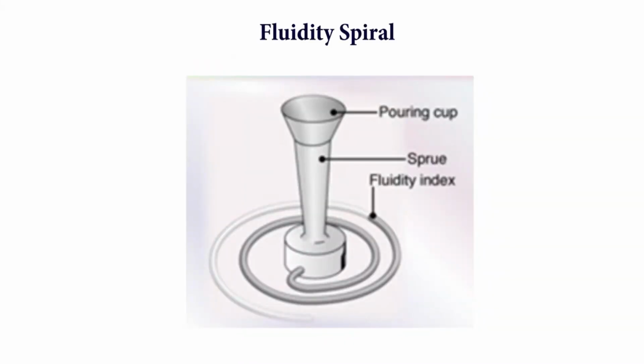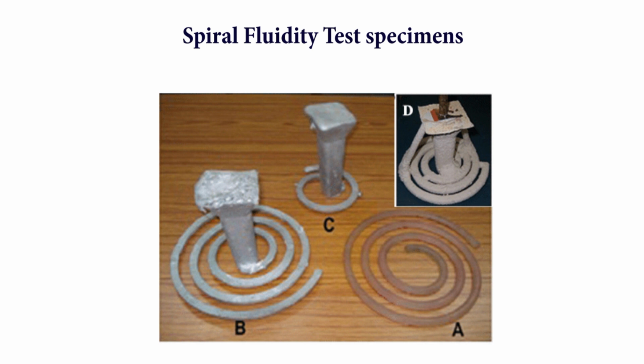Fluidity is an important characteristic of molten metals and alloys, and it directly affects the casting soundness and metallurgical quality. Fluidity is the capacity of molten metal to flow within a flow channel or inside the mold over a defined distance. The most common fluidity test used in foundries is the spiral fluidity test. A few samples of the spiral fluidity test are shown in this figure. In this method, the liquid metal is poured in a mold forming a long thin spiral, and the length into which the metal is able to run is taken as a measure of fluidity. Grey cast iron is the most fluid of all the ferrous alloys.